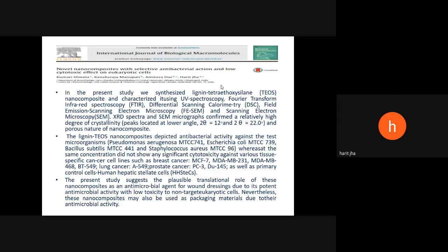In this, what we have done is that besides the synthesis of this composite, we have tested their antibacterial activity against some of the test organisms like Pseudomonas and E. coli and Bacillus subtilis and Staphylococcus aureus. And we found that they were showing antibacterial activity.